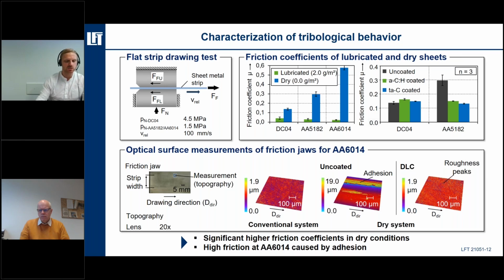For this purpose, the a-C:H or ta-C coatings were applied in the next step on the friction jaws to improve the tribological behavior. The test results can be seen here in the upper right corner. The tribological experiments with coated tools reveal that an improved friction coefficient was able to be gained. For aluminum alloys, the friction coefficient could be significantly improved compared to those uncoated tools. The optical measurements after testing revealed that almost no changes at the planar contact tool area could be detected. So it is assumed that the high hardness of the coated tools improved the tribological behavior. In particular, it is assumed that the hard materials tend to be less prone to adhesion, since the overall amount of metallic bonding forces is significantly reduced at the blank die interface.